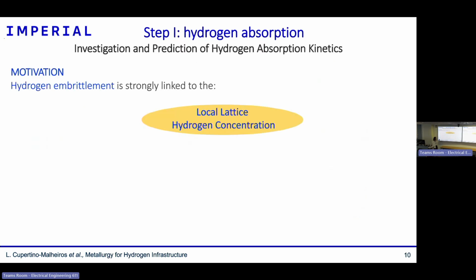All right, so the first thing you need to understand is that the extent of hydrogen embrittlement, so how severe it is, is strongly linked to the hydrogen concentration absorbed inside of metals. So that means that if you want to have a full prediction of hydrogen embrittlement for a given application, someone needs to be able to predict how much hydrogen enters inside the alloy when exposed to that environment. And that has been the topic of my earlier research, how we can make this prediction.